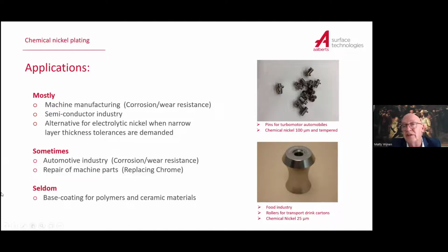It's used also in the semiconductor industry, but that's also a little bit of machine manufacturing. There's no outgassing, so it can be used there very well. Automotive: on the right side, you see pins for the turbo motor from automobiles. And thick layers, chemical nickel, 100 micron, and then even hardened. Or repair of machine parts where it replaces chrome, but it doesn't succeed in getting the same wear resistance as chrome. Another thing is it's used as a base coating for polymers and ceramic materials afterwards.